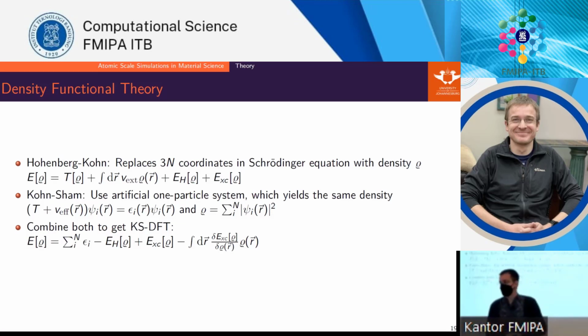And the second one is the nasty one, which is why density functional theory, while being very popular and successful, is actually a bit pathological as a method. We replace our interacting electrons with non-interacting electrons, because interacting electrons means that we have a differential equation or a set of differential equations which are all linked, right? Very nasty to solve. But if we just say, oh, we separate this, these electrons are not interacting, then the one potential term goes away. All the electrons are just moving in a mean field given by the density, right? And that is some external potential coming from somewhere. We're not looking at this.